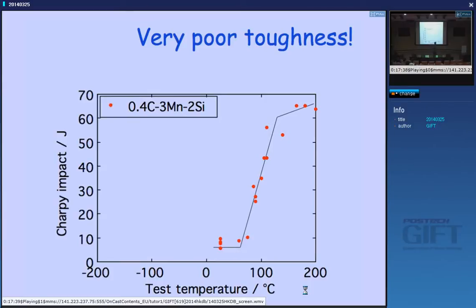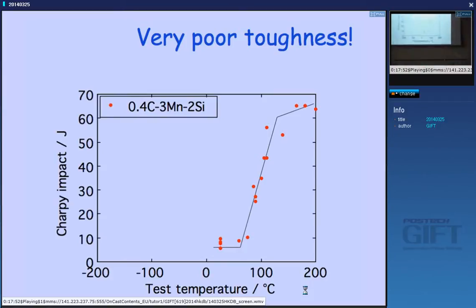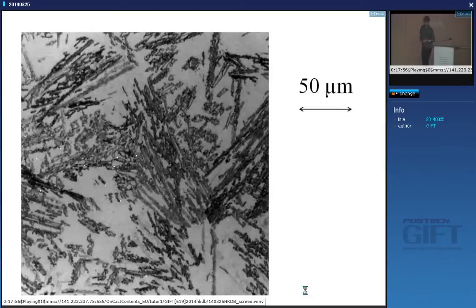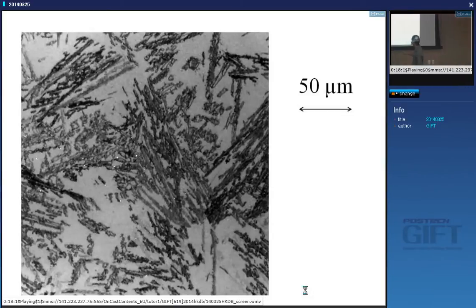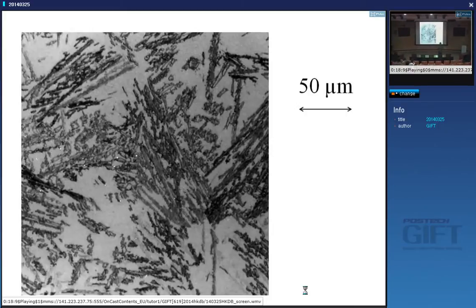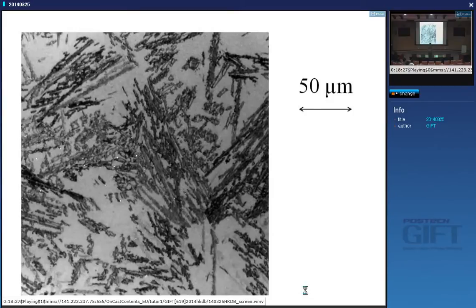The micrograph I showed you was a transmission electron micrograph, so we were looking at a very small region of the specimen. Looking now at a low-resolution optical micrograph, you can see there are large regions of austenite which are untransformed, whereas in the TEM you saw the thin films which are in regions we couldn't resolve. These large regions are of the order of 50 micrometers in size, and when you apply a stress to the material they decompose to martensite — high-carbon, untempered martensite. Imagine making a really beautiful material and then throwing in a hard particle 50 micrometers in size — that's a bad thing, and you are going to get very poor toughness.